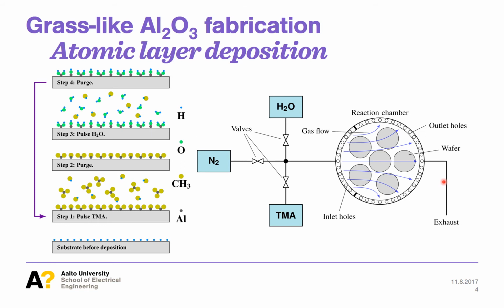Modern advanced ALD reactors have a growth speed of the aluminum oxide process of up to 7 nanometers per minute, and they get better every year. For our anti-reflective coatings, we were growing 28 nanometers of aluminum oxide in a Beneq TFS 500 reactor at 120 degrees Celsius. It is possible to grow aluminum oxide by the same process even at 33 degrees Celsius. The process becomes slower but does not lose the main features of ALD: scalability and conformality. Deposition at 80 degrees, which is low enough for many plastic optical components, would not significantly slow down the process.